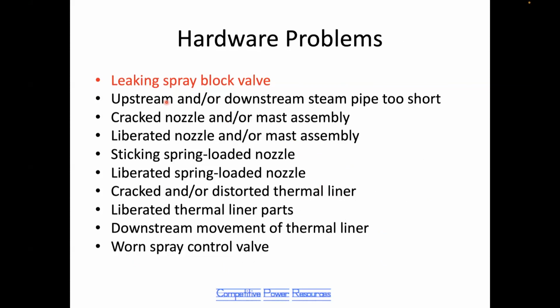The upstream steam pipe and/or the downstream steam pipe being too short is another problem. If the inlet pipe is too short, there's swirling and stratification in the steam entering the Attemperator that can disrupt the direction the sprayed water takes and cause it to impinge on the pipe wall. If the pipe is too short downstream, the water droplets that are sprayed do not have time to evaporate before they reach the downstream elbow or T or nozzle.